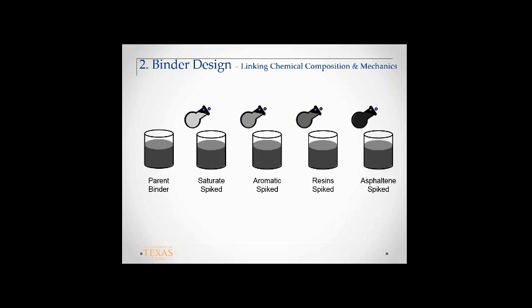Just to make it very clear, because this is important for the rest of the story: I have one parent binder, I add saturates and make it saturate spiked. To the same binder, I add aromatics and make it aromatic spiked. Same binder, I add resins and make it resin spiked, and asphaltene spiked. So in the slides that come now, when I say asphaltene or saturate or aromatic, I don't mean the component itself, I mean the binder that was spiked with that component. So we have five of these, and for the second binder another five. So we have 10 binders to go on.